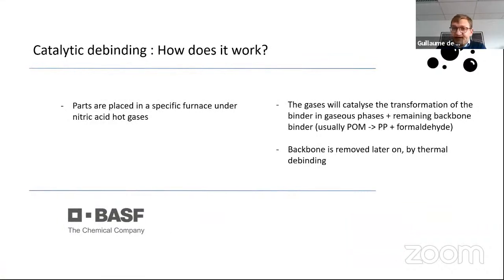The last version is catalytic debinding. So it's basically the technology of one company, which is BASF. How does it work? So the parts after printing are placed into, let's say, a specific and adapted furnace where you can inject nitric acid in a gaseous form at a few hundred degrees Celsius. And these gases will catalyze the transformation of the binder into another gas and some remaining backbone again. Usually the binder that is used for that is POM, and it will be transformed into PP plus formaldehyde. And then again, the backbone will be removed later on by thermal debinding. But again, there's a lot less binder, so it makes the secondary step, the thermal debinding, more simple.